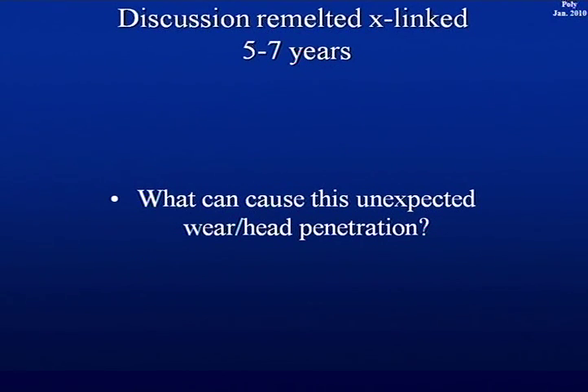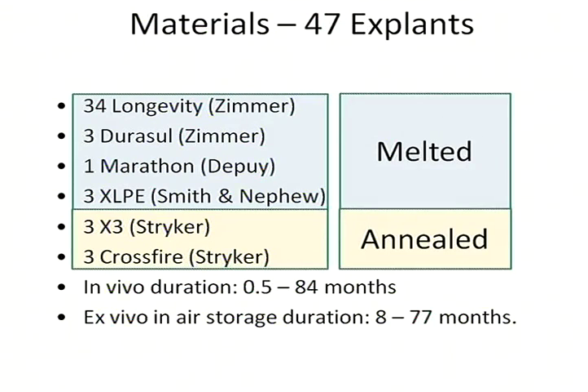But this triggered us really to look closer into what happens in the poly. What can cause this unexpected wear, head penetration? So we looked at 47 explants in the lab. You can see here 34 longevity, 3 Durasul, 1 Marathon, 3 XLPE, melted, as I told you first, and then 3 X3 and 3 Crossfire, annealed. They have been in the patient between half a month and 84 months, and then we put them, after some initial measurements, on the shelf in air, and they were stored between 8 and 77 months.